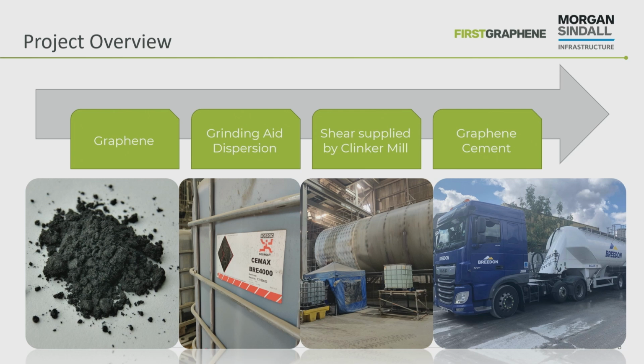point in the project was, how do we get the graphene into the cement plant? Usually when you've got graphene, you need a liquid addition point, so you need to get it well dispersed before it goes into the cement plant. And there's only really one point to do that. You can put it into the water, which is sprayed into the cement mills, but there's also existing grinding aids which are used inside the mills. So we thought that is really the only point in the cement production process where liquid additives are used.